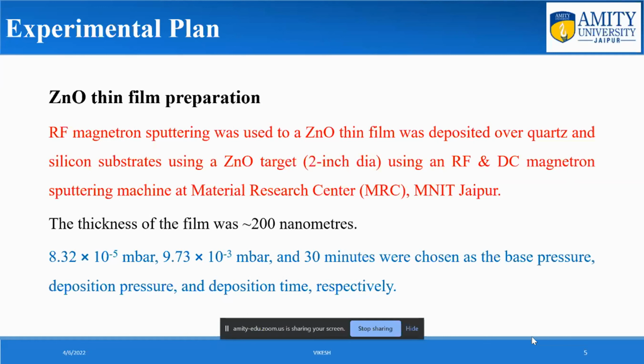After deposition, the irradiation of ZnO thin films: these thin films were irradiated with a 220 kilo electron volt ion beam at various fluences like 1E13, 1E14, and 1E16 ions per centimeter square using a low energy ion beam accelerator at the Inter-University Accelerator Center in New Delhi, India. This is the setup for ion irradiation at IUAC New Delhi. And now, results and discussions.